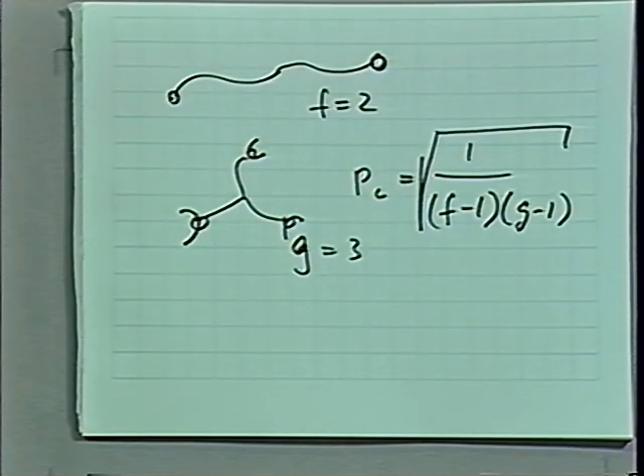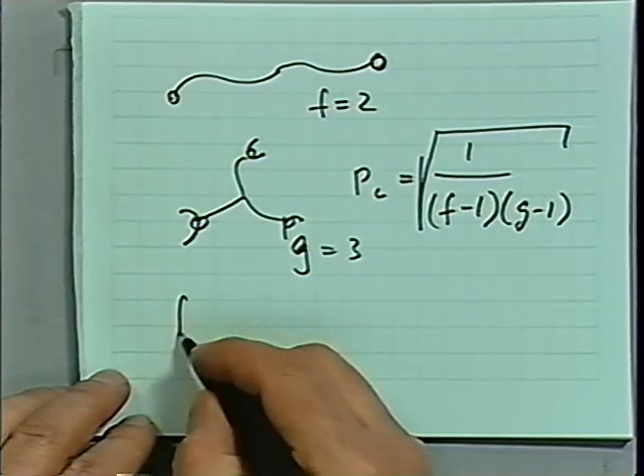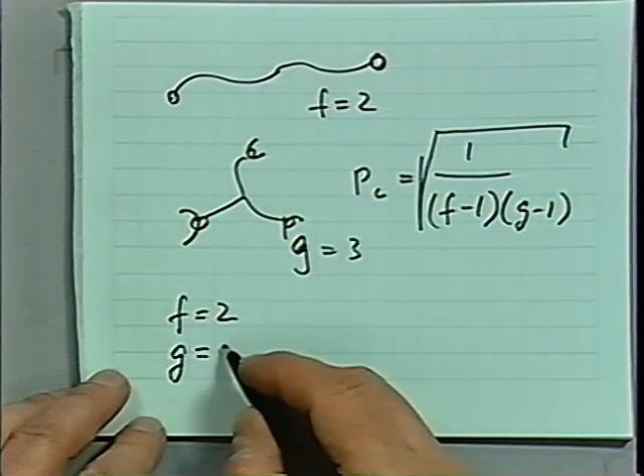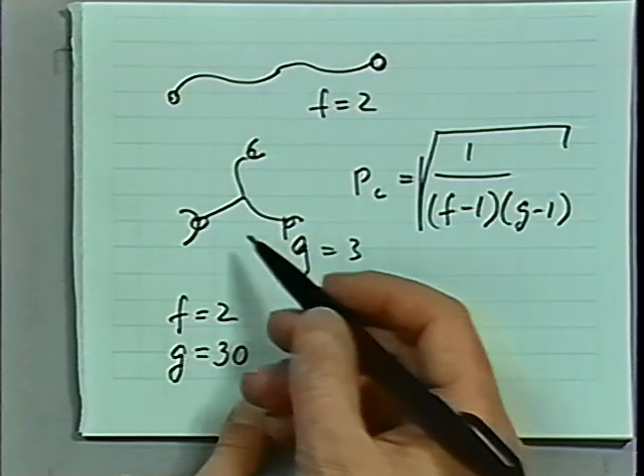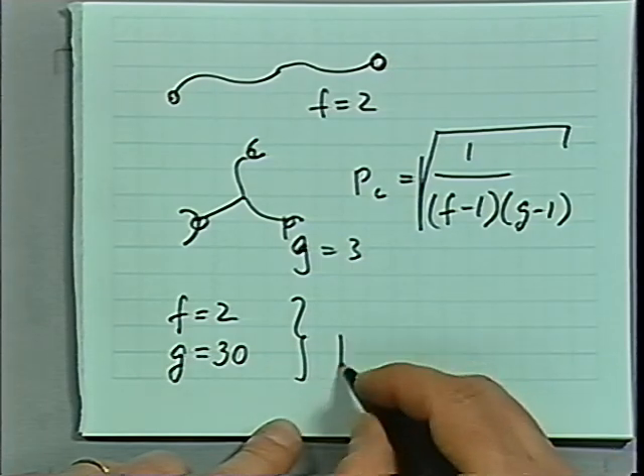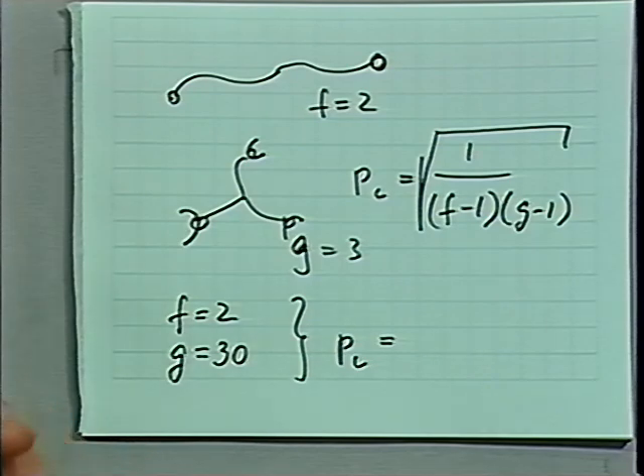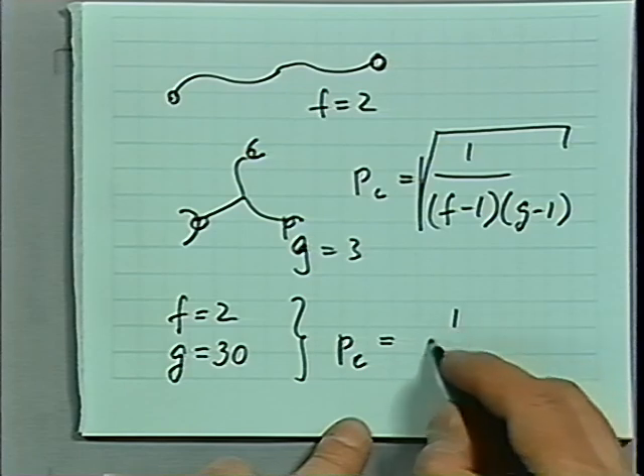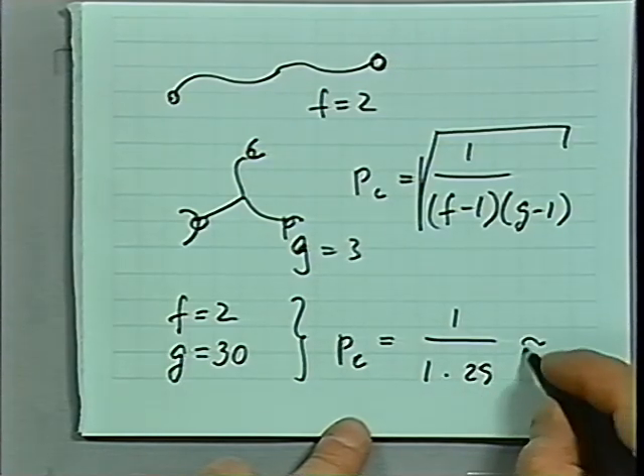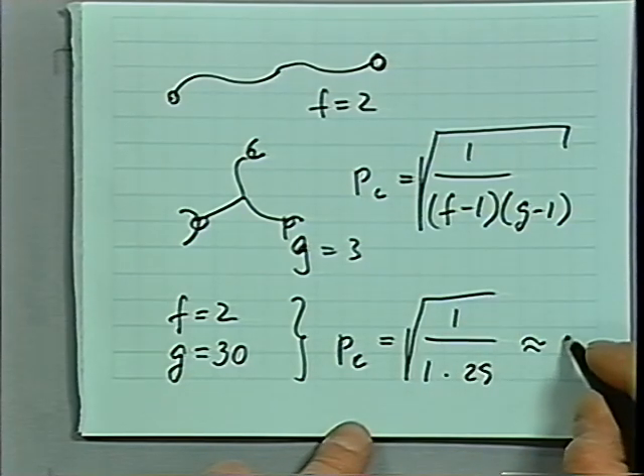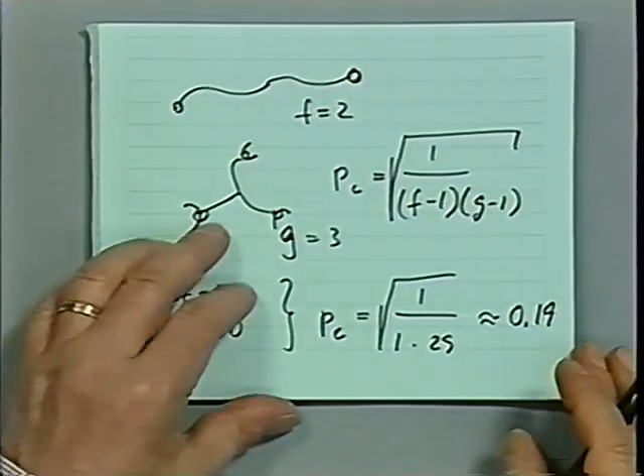Coming back to the sample of De Rosa, where, say, F was 2 and G was about 30, the tough gels, which have lots of reactive ends, not just 3 reactive ends, many of those, then the conversion for a system with a balanced stoichiometry at the gel point would be 1 over 1 times 29, and if you evaluate the root of that, it's about 19%. It's 0.19. And that's about what we are finding in those experiments. It's not really a proof that this theory is correct. There are strong believers of that type of theory and some very strong disbelievers of that theory. But somehow the magnitude of the critical conversion agrees with what we see in experiments.